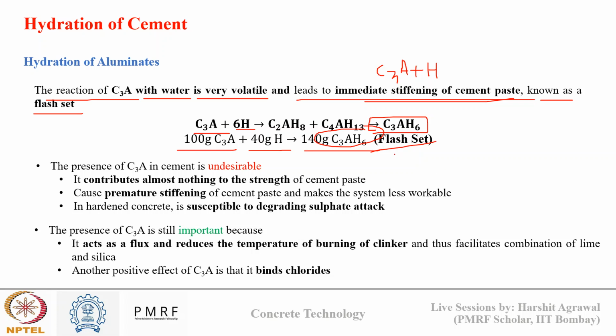And why is it a problem? Because when we talk about concreting, we are mixing concrete at a certain location and pouring it at a different location. There are cases when we need to transport the concrete from one place to another. If my concrete sets instantaneously, transportation becomes a problem. If it is already set, we won't be able to pour it into big molds, and it won't flow and cover the entire space inside the mold to form the definite shape that we want. So that's why we don't want flash setting to happen in concrete.